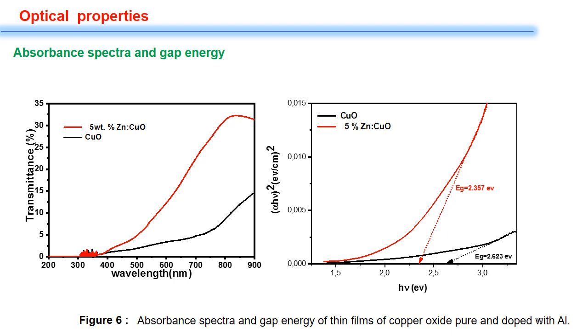According to optical properties, we can determine the transmission spectra and gap energy. This figure presents the variation of transmission as a function of wavelength. All films present an average transmission in the visible range. From the transmission results, we can calculate the gap energy using the Tauc relation, by plotting (αhν)² as a function of photon energy. By the extrapolation method we get the gap energy, which varied between 2.62 electron volts and 2.35 electron volts.